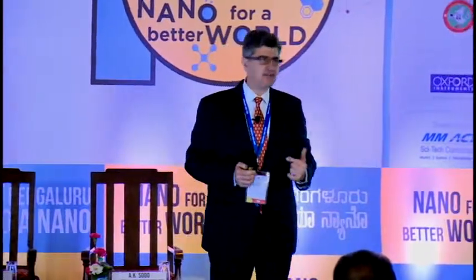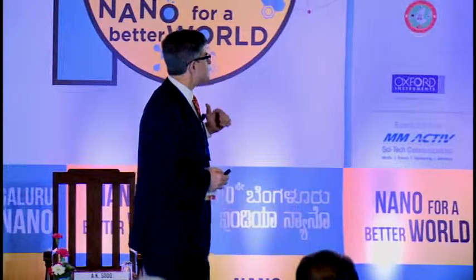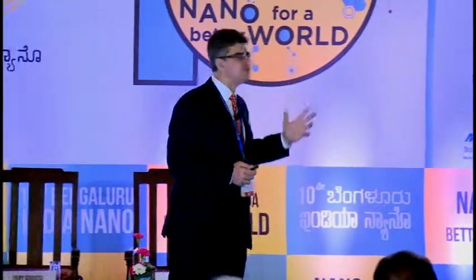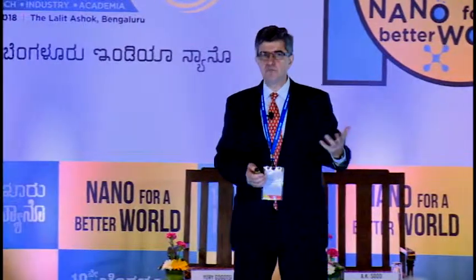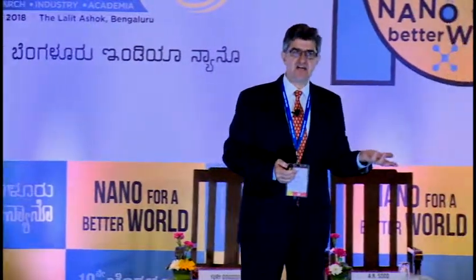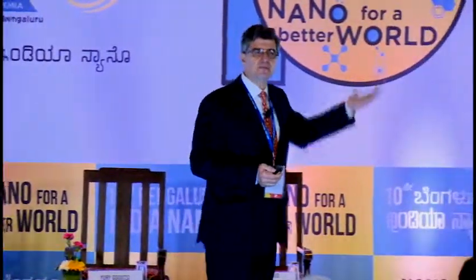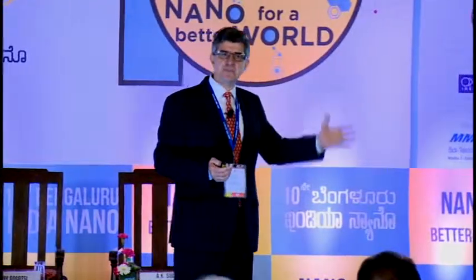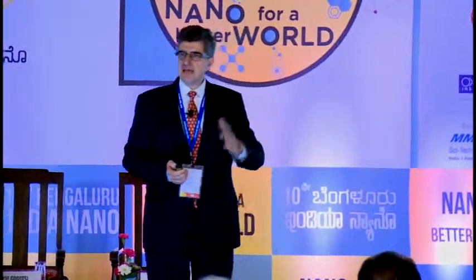So basically, it can charge within 1 millisecond, the entire device here. But it also gets, for example, in this case, about 1,500 farad per cubic centimeter, which is roughly an order of magnitude more than an activated carbon-based supercapacitor can give, because of this redox wave. It combines redox storage and double layer storage.